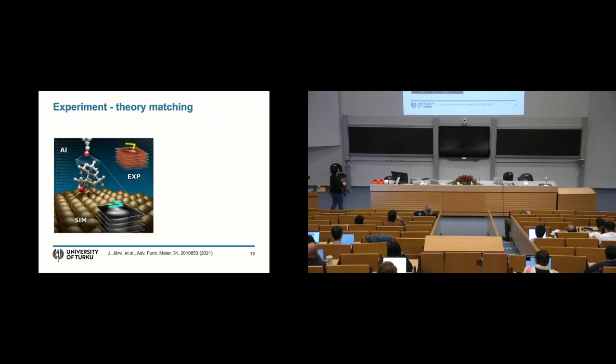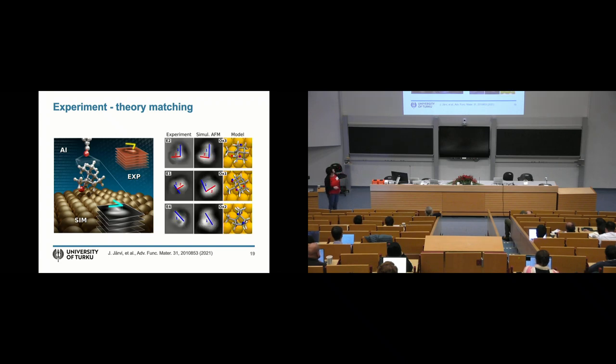Then we did some laborious image matching for all of our five potential candidate structures. We generated simulated AFM images in a stack as you withdraw the tip above the molecule. And then we compared to experimental image stacks of the similar kind. And this is what we found. We found that there were three simulated structures where the simulated AFM somehow matched the experiment. It's disappointing that they're all so blobby and really difficult to interpret.